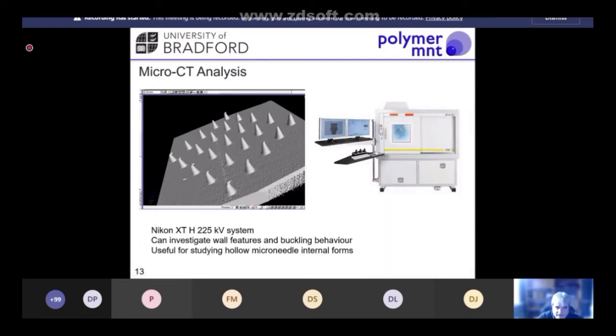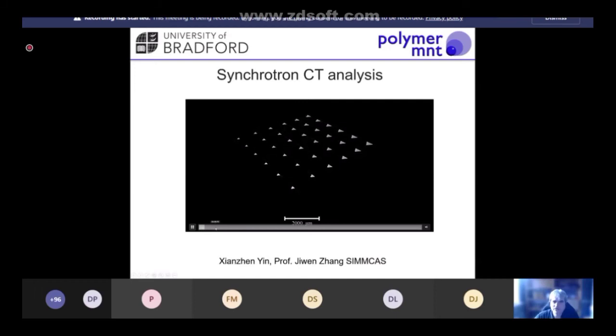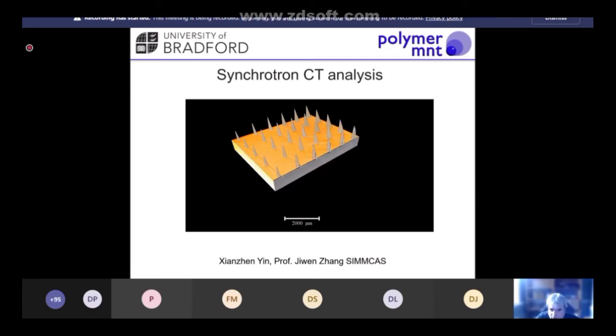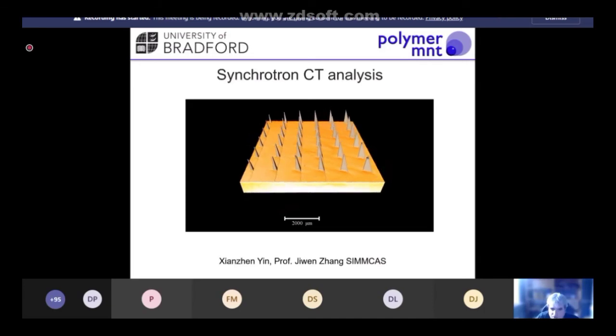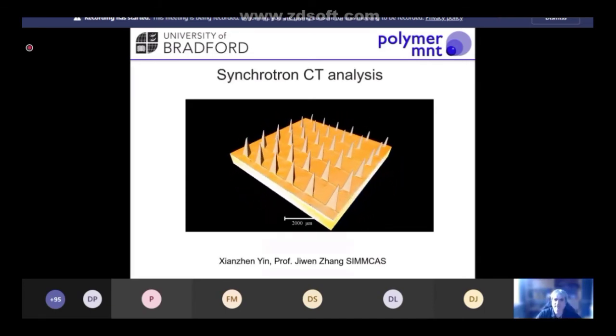We also have a micro CT system. So this allows us to volumetrically measure our microneedle arrays. So if we have a drug crystalline solid within our microneedle arrays that has a significant change in density from our polymer carrier, we can use the micro CT to look at the distribution of that drug within our microneedle arrays. So it provides this volumetric imaging behavior that allows us to investigate in more detail. In fact, we can go one stage on from that, and we can look at synchrotron CT analysis. So this was one of our microneedle arrays that was measured by Professor Jiwen Zhang in SIMMCAS in China. So this is once again a full volumetric measurement of the microneedle device, then we can use this to measure geometry and drug consistency within the device.